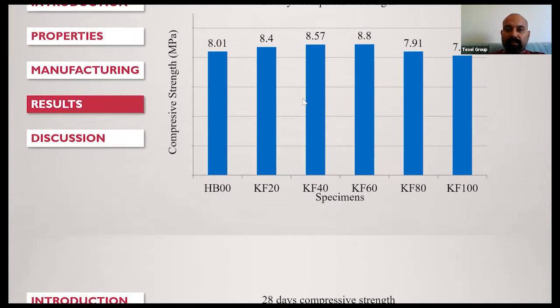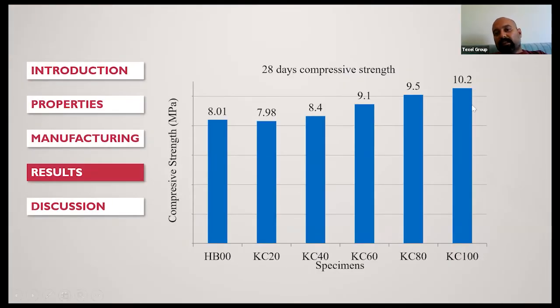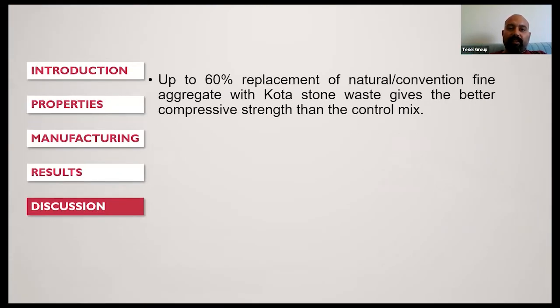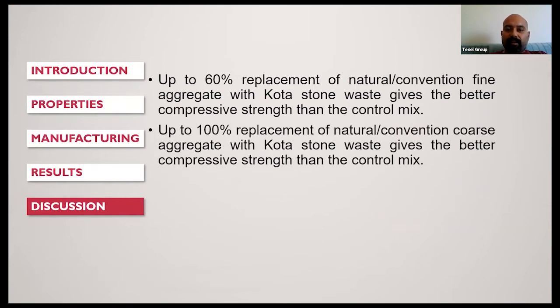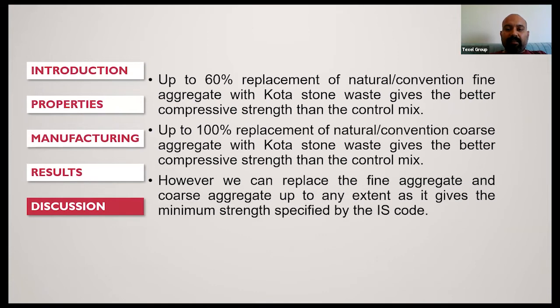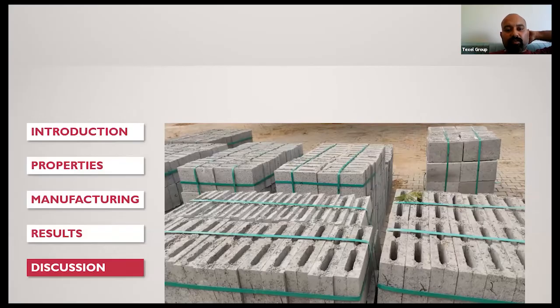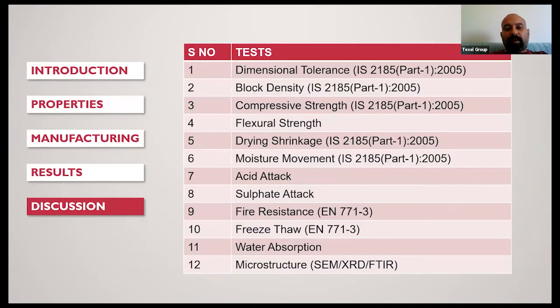In case of coarse aggregate replacement, 100% replacement shows the best results for compressive strength. In conclusion, we can use 60% replacement of fine aggregate with Kota stone waste, and 100% replacement of conventional coarse aggregate with Kota stone waste. However, we can replace fine and coarse aggregate up to any extent because it still covers the minimum strength specified by Indian standards. These are the hollow blocks produced, and these are the future scope of study, where we can have intensive research on different durability tests.